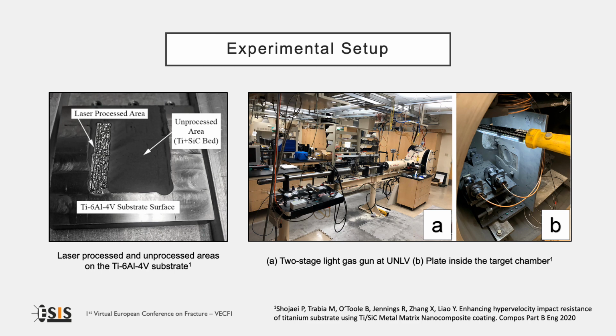The experimental apparatus is shown in this slide. Pure titanium powder with an average size of 45 microns was mixed with 5% weight silicon carbide nanoparticles, which has average size of 40 nanometers, using a ball milling for 4 hours, without a protection atmosphere. 200 microns of the mixed powder was deposited on the titanium 6-4 plate, which has a thickness of 12.5 millimeters. Afterwards, the surface was processed with selective laser melting.